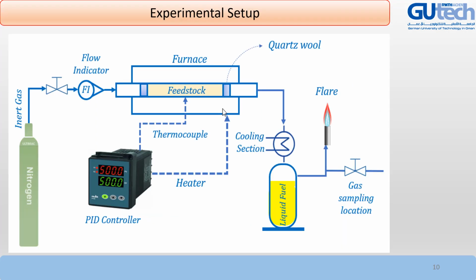Experimental setup includes the reactor. The reactor is a tubular reactor made from alloy and sometimes from quartz. In this case, we used metal as the material of the reactor. The reactor is inside the furnace, an electrical furnace, for heating up the reactor. Inert gas can be used for pyrolysis, and the product will be condensed in the condenser to separate liquid fuels from the non-condensable gases.